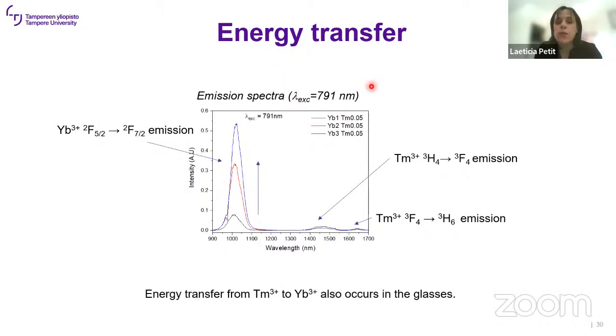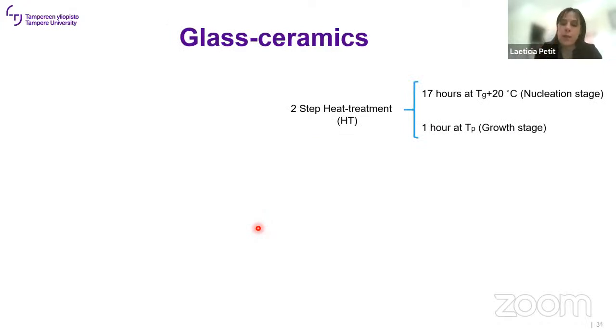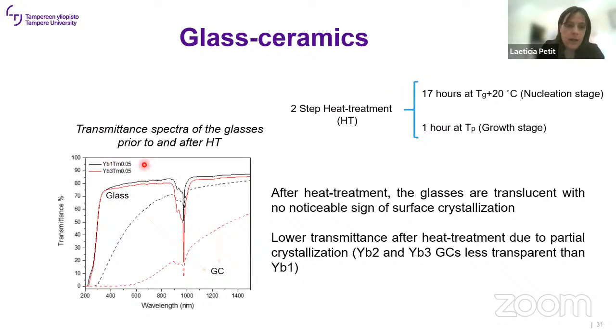We also measured the emission spectra using 791 nanometer pumping. We have the typical emission from the thulium, but we also got an emission at 1 micron. This is due to the emission from ytterbium, confirming the energy transfer from thulium to ytterbium in the glasses. We then tried to make the glass ceramic, using the two-step heat treatment as we did in the past. Here is the transmittance of the glasses, the two extreme glasses, prepared with 1 and 3 mole% of ytterbium. We have a decrease in the transmittance. The glasses become translucent after heat treatment with no sign of surface crystallization, and the lower transmittance is due to the partial crystallization of the glass.